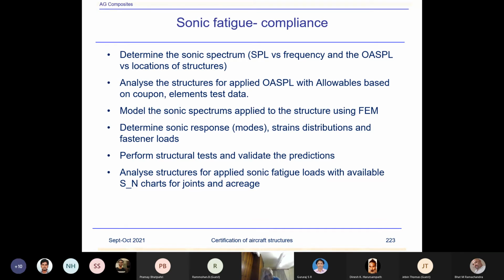So what normally is done, you generate the sonic spectrum for a particular part at a particular location. Based on that, determine the fatigue stresses, because that is related to RMS. And then you have to determine, based on that RMS level, what is my allowable RMS for a particular part, a structure. For the number of cycles, normally it will be something like 10 to the power 8, or around 10 to 100 million cycles, which would be usual for sonic fatigue.